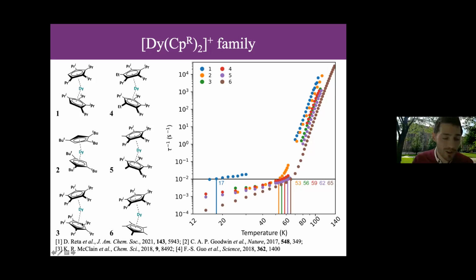But by the time we got to there, the Jeff Long and Ben Harvey groups from California had added a few more examples of dysprosocenium single molecule magnets, as had Richard Layfield's group in Sussex. And so we have a family of these materials which have very similar and yet in some senses quite different relaxation properties. So on the right-hand side, we have the relaxation rates experimentally as a function of temperature. And the compounds here are ordered 1, 2, 3, 4, 5, 6 based on their 100 seconds so-called blocking temperature, which is just a convenient way of defining some benchmark.